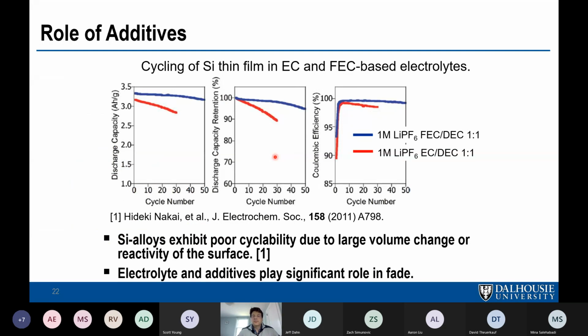The other important component to making alloy material cycle well is electrolyte. These things are electrolyte additives. The alloy is expanding and contracting and disrupting the SEI constantly because of this. And some additives can improve cycling a lot. One of the most well known is FEC. And here's one of the first papers about FEC. You could see this is the percent capacity retention without FEC and with FEC, and it makes quite a big difference also to the Coulombic efficiency.